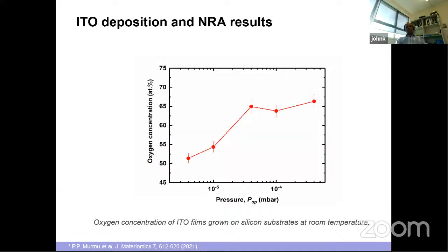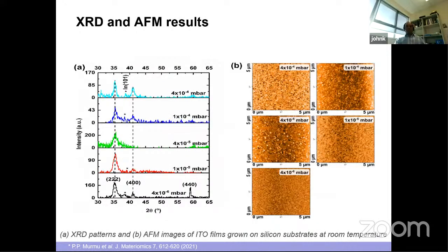The way we made indium tin oxide is we varied the oxygen concentration via the chamber pressure. Then you can see that we can nicely tune the oxygen concentration in the film, which gives us better controllability in forming indium tin oxide. You can see the nice structure, and the reflections match with the JCPDS pattern. But what is more important is that the 440 reflection was only observed at the pressure of 4×10⁻⁶, where we believe the sputtered atoms have more energy than in normal films grown at high pressure, with indium-rich metallic clusters. So you can see some sort of cluster formation, similar to copper iodide.